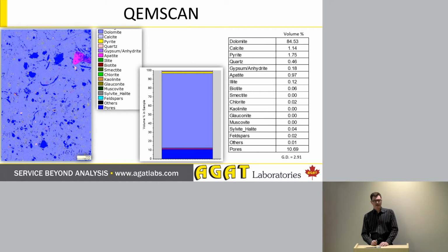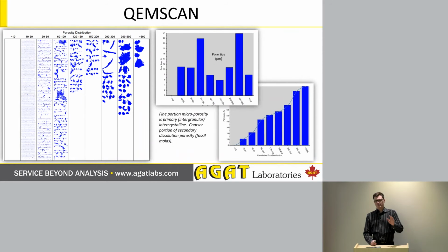In this example, we're looking at a map of a thin section in a dolostone with a secondary dissolution porosity. Geologists will recognize that we have shell fragments that have dissolved out, and the dark blue is the porosity, and you can see that there are still even shell fragment shapes present within those. Well, what we can actually do is tell the system, show me all of the porosity spaces. We could do this with any mineral, but as an example, let's use porosity. And what it'll do is it'll categorize them by size and also give us a size distribution for each of those, throughout the porosity size ranges. In this example, we can clearly see there's a bimodal distribution of porosity size, and the reason, of course, is that the secondary dissolution is much, much coarser than the primary porosity.